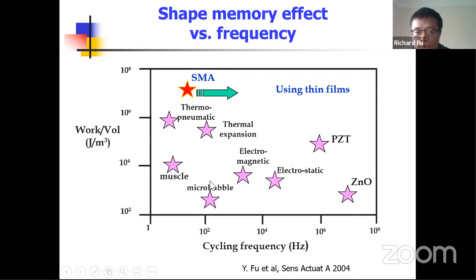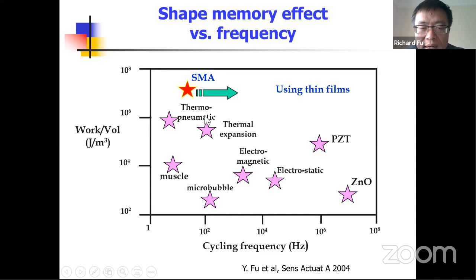One problem for MEMS application is that shape memory alloy actuation is based on thermal effect. So we need to use temperature, heating up and cooling down. For all thermal microactuators, the problem is the frequency, because you're heating up very fast, but the cooling down is very slow. So that means the cycling is very difficult. Compared to other materials, we need to increase the frequency.